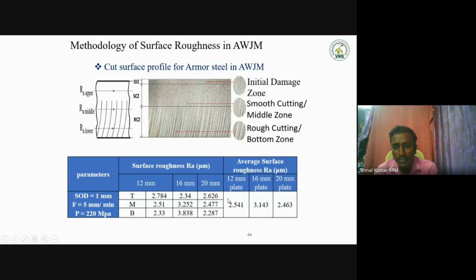These are the average surface roughness values: 2.541, 3.143, 2.463. So 2 is acceptable, but 3 is not acceptable. These kinds of traces are identified in SEM images, but they are not visible to the eye. Only in the final SEM image can we identify the water traces. Generally, a surface roughness of 2 is acceptable for the cut surface of the water jet machine. We also achieved this.